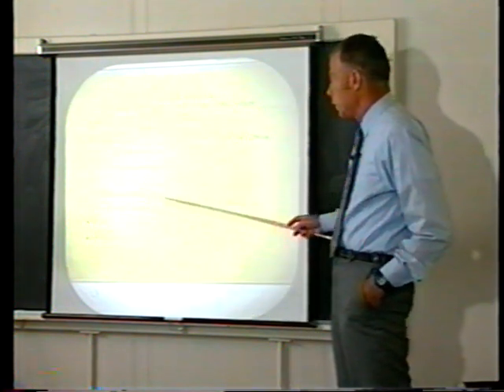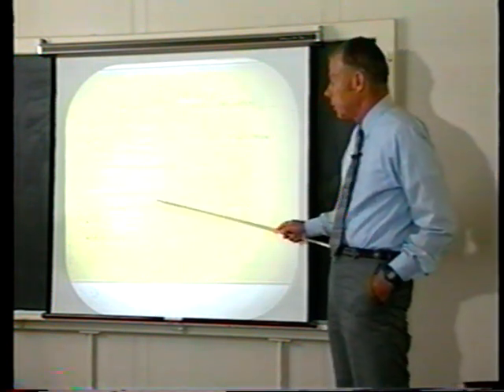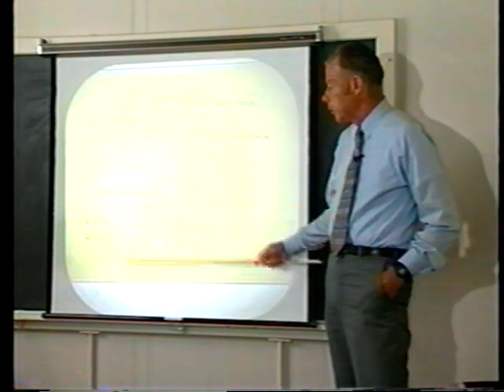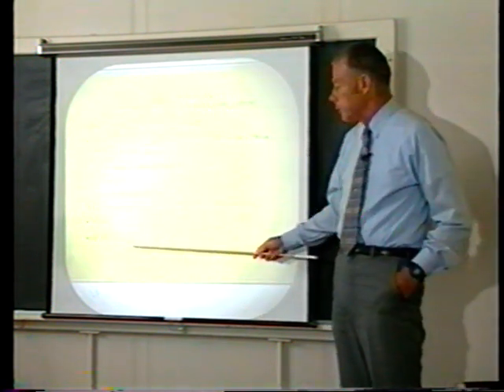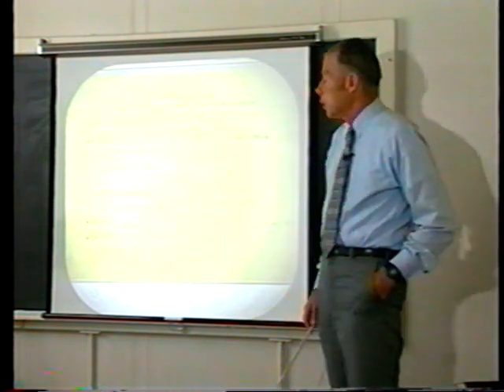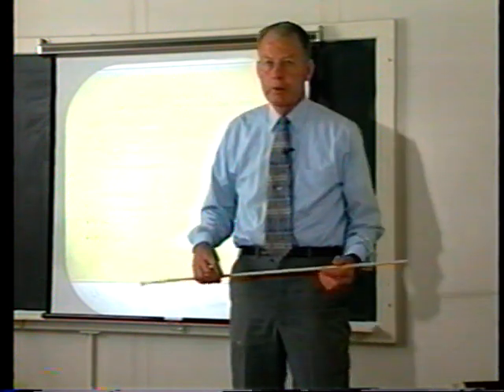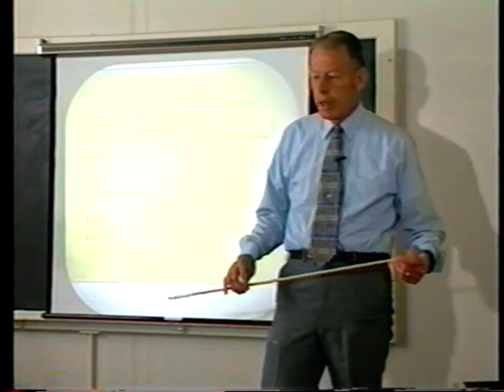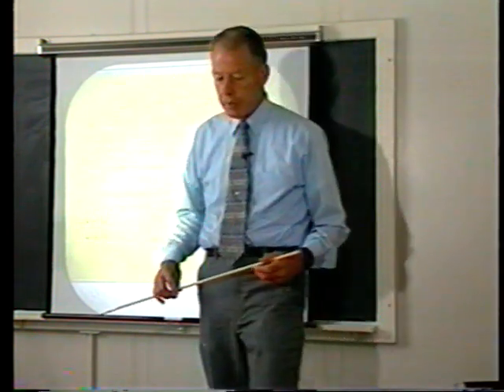Now Celani, who's not too far away in Frascati, Italy, has also been using the design suggested by Preparata. He's been studying palladium as well as palladium-yttrium alloys, and he reports up to 200 watts of excess heat. So we see this thin wire design in Italy where progress is being made perhaps to get a reproducible excess power effect and a very large effect at that.